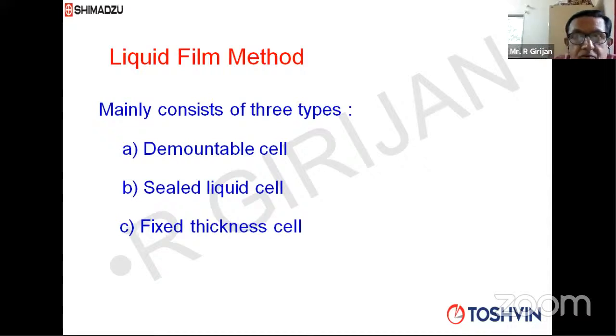But if you really want to do a quantitative analysis, you have to go for a fixed thickness cell. Fixed thickness cell means you cannot open the cell. It is totally fixed by the manufacturer. You cannot open it. It's only for 100% quantitative analysis. So use the fixed thickness cell for quantitative analysis, where you cannot open the cell, and use a demountable cell for qualitative analysis, where you can open the cell, take out the crystals, and wash them. And even for the fixed thickness cell, there is a washing procedure without opening the cell.